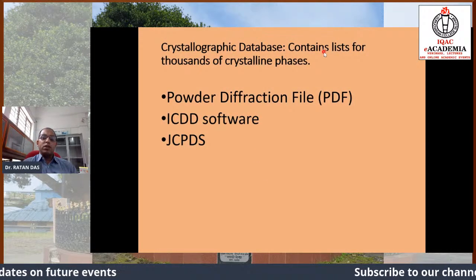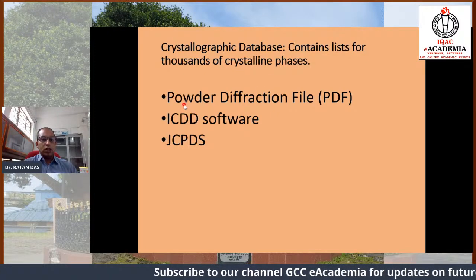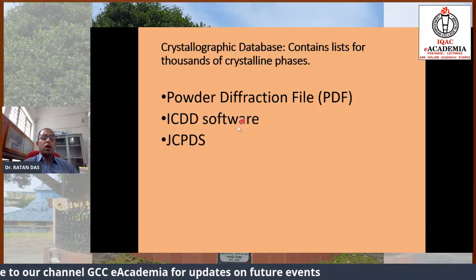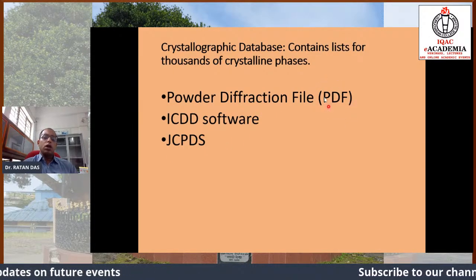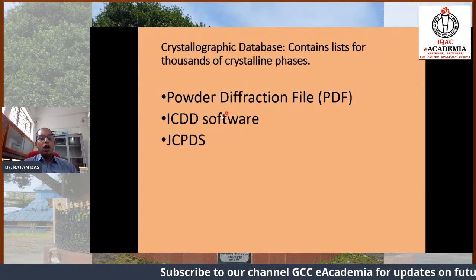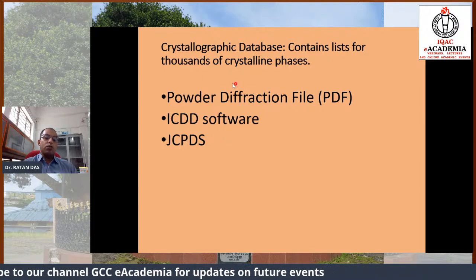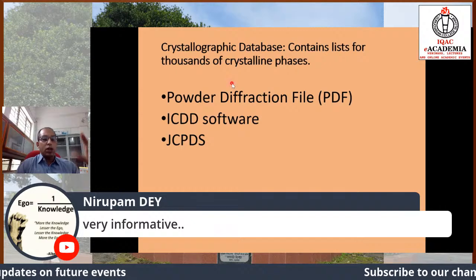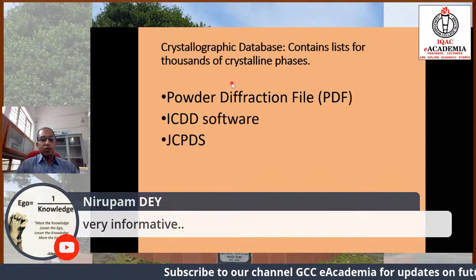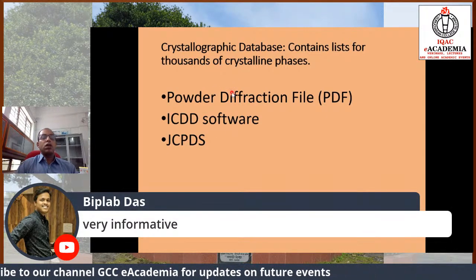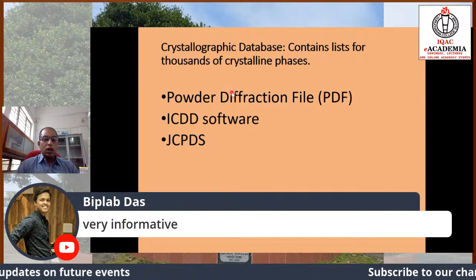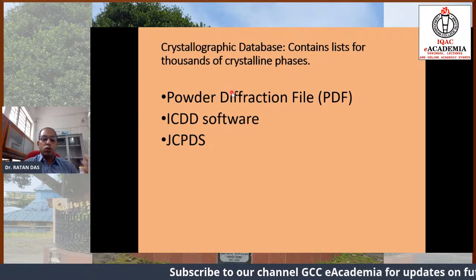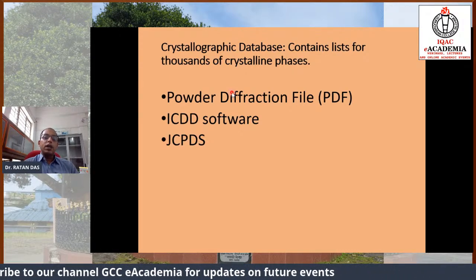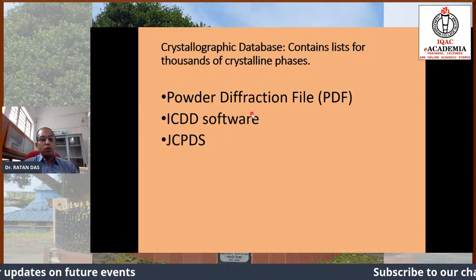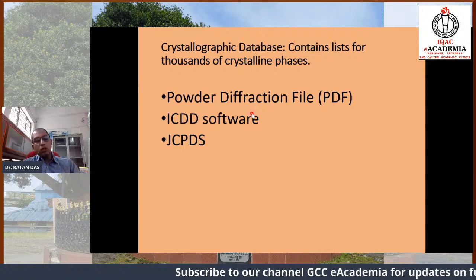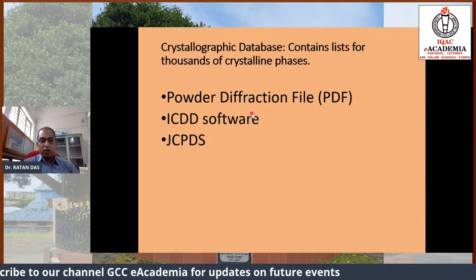So there are some crystallographic databases which contain a list of thousands of crystallographic phases. These databases are ICDD software, JCPDS software, the Powder Diffraction File, PDF. This is not the PDF file that we usually mean. It is a powder diffraction file, and these are some costly softwares. But these are available in different libraries, or with the instruments where an X-ray diffractometer is available. They supply or they study the matching with those patterns. Or if you are present near the instrument, then you can also match your sample with the particular pattern. And by matching with this particular pattern, we can index our diffraction data.